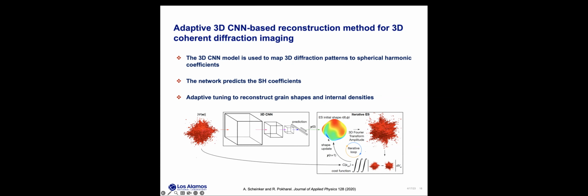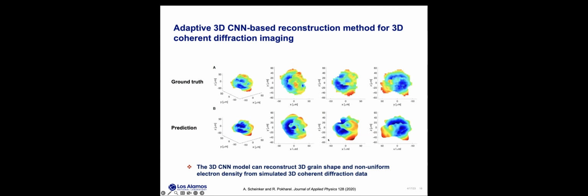So here are some example comparisons between the ground truth and the ML predictions, and you can see that this CNN combined with the adaptive feedback approach accurately predicts these very complex shapes, even though the training set had smoother shapes. These test sets were obtained from experimentally measured crystals from a polycrystal, so they had very complex shapes, and the predictions were able to predict both the shape and the phase fields and displacement fields inside